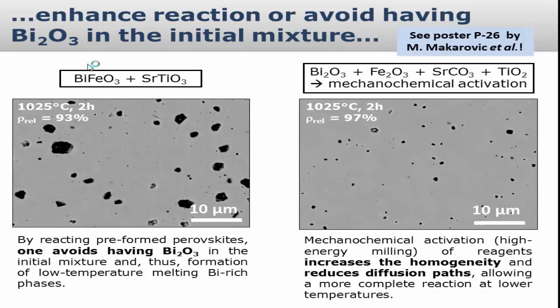But you should allow that they react before you go to sintering. And this is another case. The second possibility is just don't use bismuth oxide in the initial mixture. This will prevent forming liquid phases because you don't have the main component, the Bi2O3.